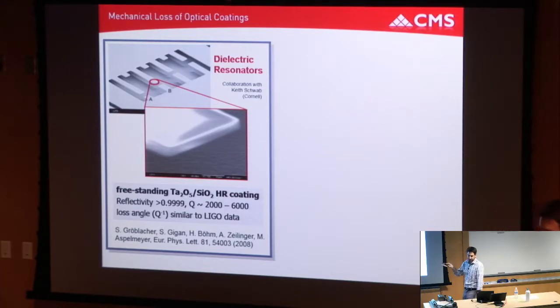We borrowed from the precision metrology community early on, so we would take just standard sputtered silica tantala multilayers, deposit on a silicon wafer, lithographically pattern cantilevers, etch down through that multilayer, and isotropically etch away the underlying silicon, and you end up with cantilevers of just purely coating material.